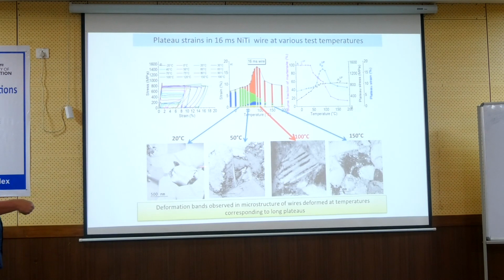The aim of this article was to explain why we have such different plateau lengths. This TEM gives us some clue. Suddenly, around 100 Celsius, when the plateau length becomes long, there is a lot of dislocations, which suggests some plasticity has occurred. So this evidence suggests that plasticity did occur, but we needed something systematic. So the Chinese student did it on different wires. This is for 10 milliseconds, a very hard wire with very high yield stress. This is for 20 milliseconds. And you see the maximum is at high temperature everywhere, but here it is at 200 Celsius and here it is around 50 Celsius.